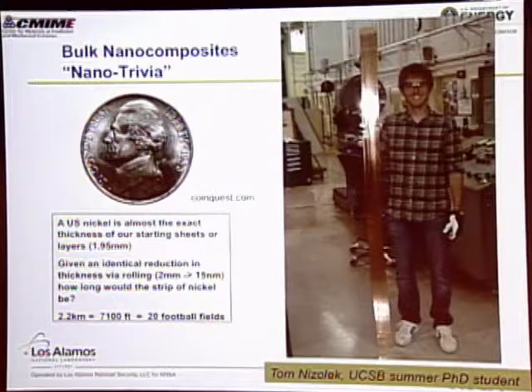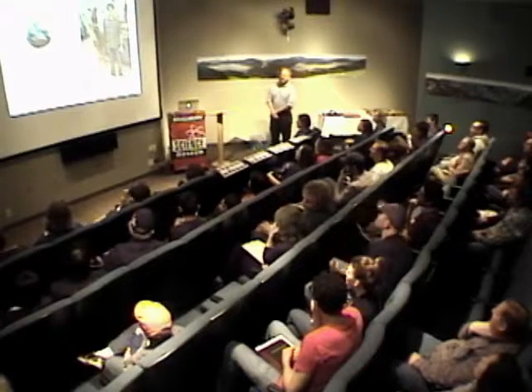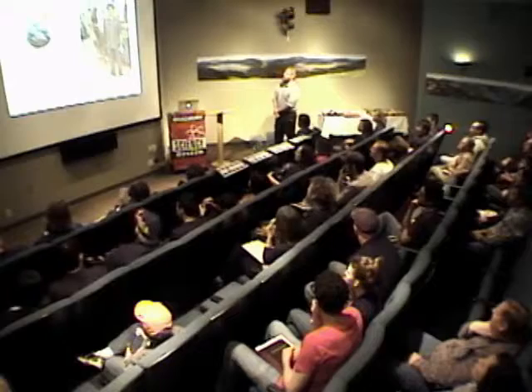So a little bit of nano trivia here. We can now make these kilograms of nanomaterials, essentially nanocomposite in the quantity of something that looks like a ski. And what does it mean to be able to roll this out to this point? Well, if we were to take a nickel, which is the same thickness as our starting materials, and roll it out the same amount that it takes to make this material, we would have to roll it out 2.2 kilometers, almost a mile and a half, in order to get to that point. So we've really, really tortured this poor material. But you'll see the types of properties that we can get out of this are not the same as what you would expect with copper or niobium alone.